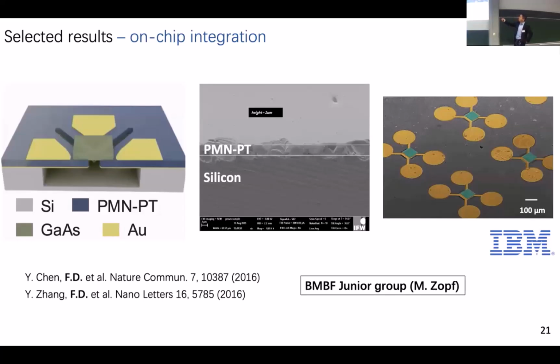Another side advantage is that, with this 100 micron scale bar, you can integrate arrays of devices on top. Another side advantage, which turned out to be a big advantage, is that we have two pairs of fingers. This is one pair, this is another pair. By controlling the voltage, you can decide in which direction you want to give more strain, which means that if the quantum dot wave function is not symmetric, for example elongated, you can apply strain to recover the symmetry of your electron and hole wave function. That was actually quite interesting.